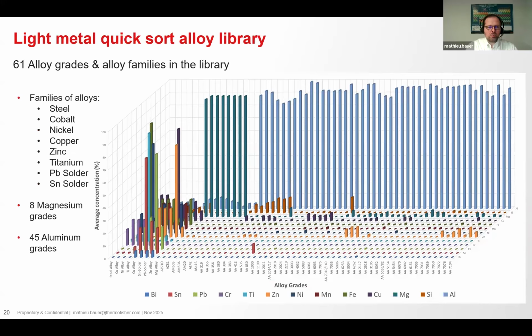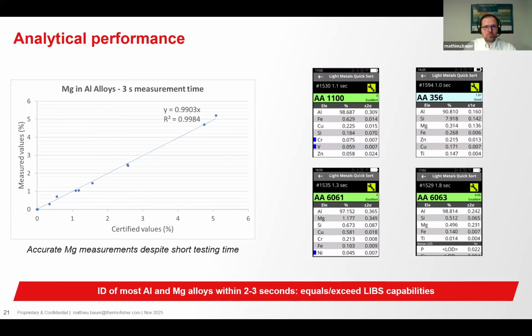So we have a specific alloy library that is focused on lightweight metals. It includes 61 alloy grades and families of alloys. So we have 8 families of alloys for base metals, 8 common grades of magnesium alloys, and 45 common grades of aluminum alloys in this library. Magnesium was for a long time the most challenging element in handheld XRF. Historically, like 10 years ago, it took about 10 to 20 seconds to detect magnesium at a level of 0.5%. Now, using this mode, it's possible to measure magnesium pretty accurately within 3 seconds of measurement time.